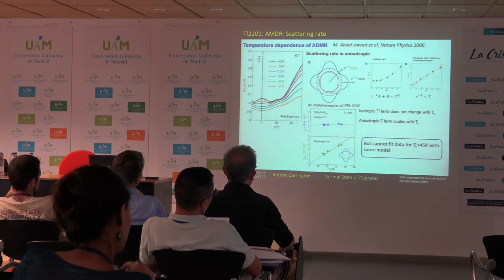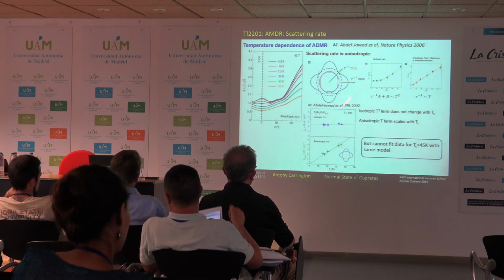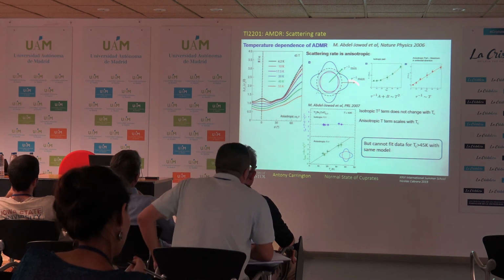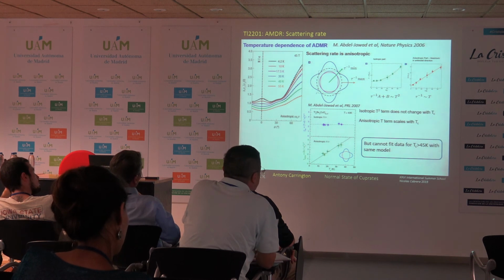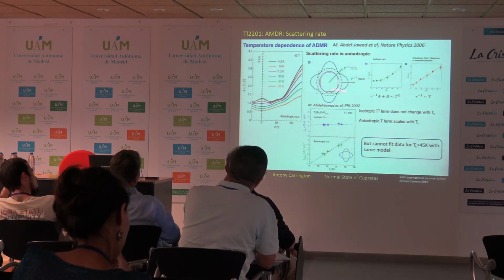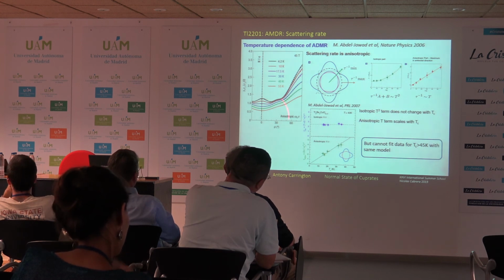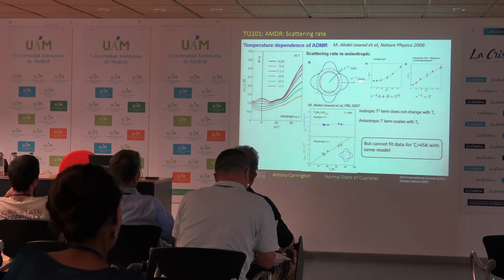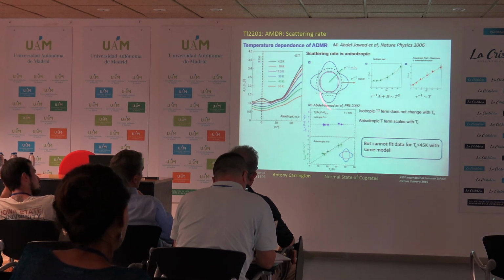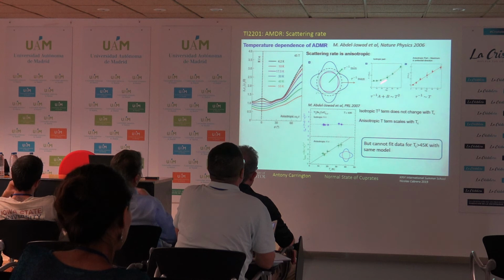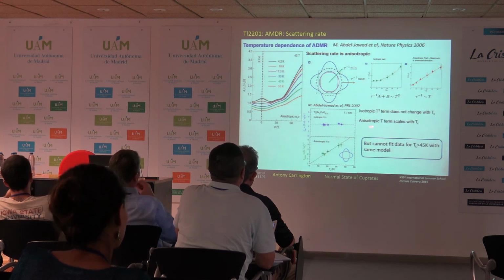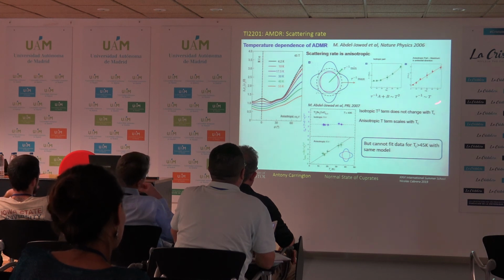Okay, I've got 5 minutes left. One thing we found out from angle-dependent magnetoresistance measurements was that not only could you work out what the shape of the Fermi surface was, but you could also work out what was happening to the scattering. So you could only model the magnetoresistance if you had 2 bits to the scattering. Basically the scattering was anisotropic, and this anisotropy changes with temperature. You could model it as a component that's isotropic, and the isotropic part varies like T squared, and the coefficient of this T squared doesn't vary with T. And then you've got an anisotropic part, which varies linearly with T and scales linearly with TC.